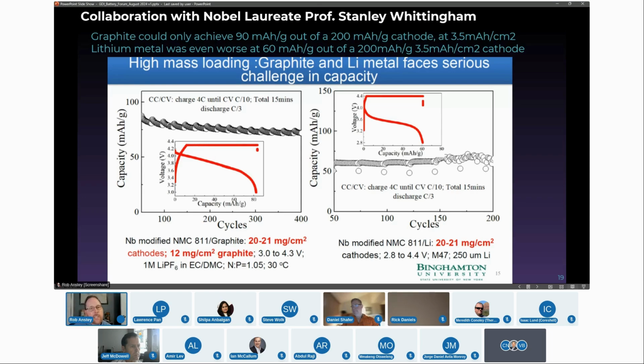Every single time 4C. And what you see is graphite, okay, it's not horrible. It's getting about 80 milliamp hours per gram out of a 220 cathode. Not great, but this is with a fancy new electrolyte and a fancy new niobium-doped NMC 811 that sort of fought against lithium plating. And the lower cutoff voltage was only 3 volts, and it was a very thin anode. That was only 12 milligrams per centimeter squared. So that's under 3 milliamp hours per centimeter squared. But they considered that somewhat high mass loading compared to power cells.